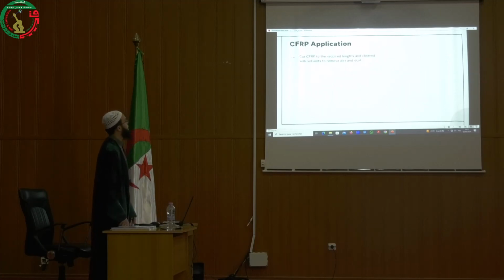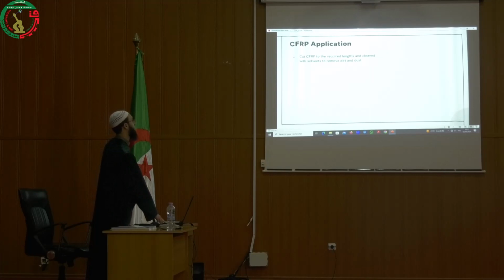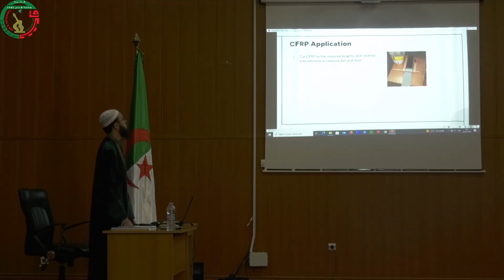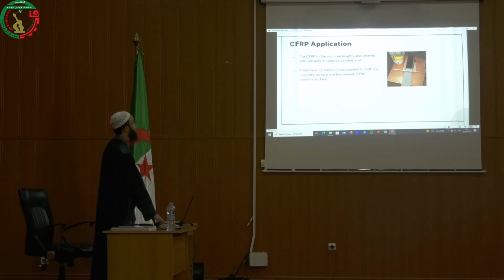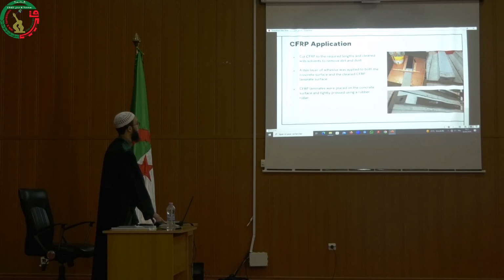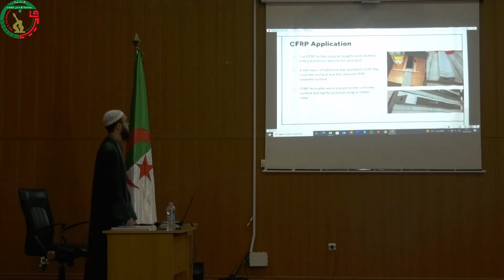The process didn't end with the manufacturing, so we need to apply the CFRP laminate to the tension surface. To do that, we must cut the CFRP to the required length and clean it with solvent to remove dirt and dust. Then a thin layer of adhesive was applied to both the tension surface and the clean CFRP laminate surface. After that, the CFRP laminates were placed on the tension surface and tightly pressed using a rubber roller to avoid air bubbles.